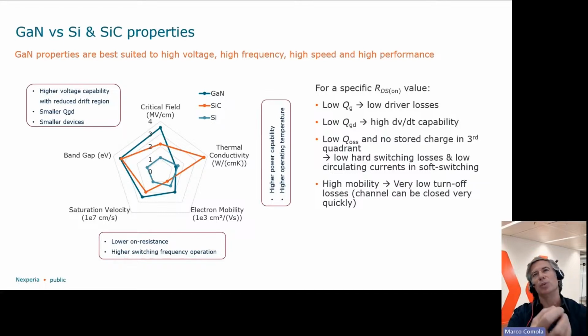So practically, if I have to give you an idea in terms of products, in terms of devices, for a specific on-state resistance value, you have a low gate charge using the gallium nitride versus the other compounds. So you have low driver losses, and you have low QGD, so you have high dV/dt capability. You have low output charges, so no storage charge in third quadrant, and you have low hard switching losses and low circulating current in soft switching, and you have high mobility. And high mobility is translated, of course, into very low turn-off losses, so the channel can be closed very quickly. So again, this is translating into lower losses and higher efficiency.